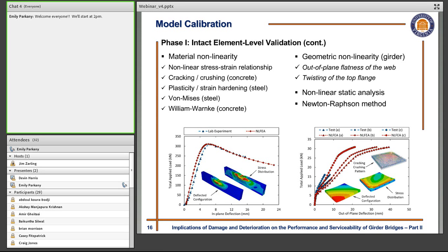Other than that, as you can see in this figure, they had a limitation on the amount of load that they put on this structure in their test setup. But in the numerical model, our model was able to capture the full nonlinear behavior of the system up to the failure of this specific slab, which was caused by a combination of material yielding in the reinforcement, cracking in the concrete deck, and crushing on the top surface of the deck.